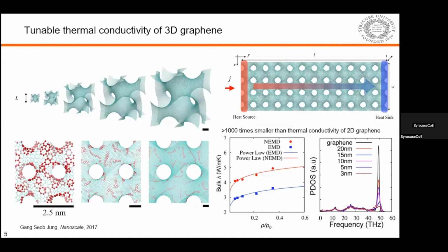Besides mechanical properties, we can also set up simulations to characterize the thermal property. We set one heat source and one heat sink, and we study how those architected structures conduct heat from one end to the other. Once you create the 3D geometry from the 2D graphene, you also introduce a lot of defects, like 5-rings and 7-rings, into the structure. Those defects scatter the phonons and make it difficult to conduct heat from one end to the other. That's why the thermal conductivity is over 1,000 times smaller than the in-plane thermal conductivity of 2D graphene. Once you decrease the density, the thermal conductivity decreases further because you have fewer phonons.